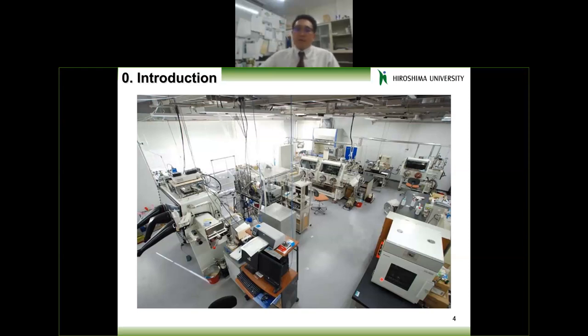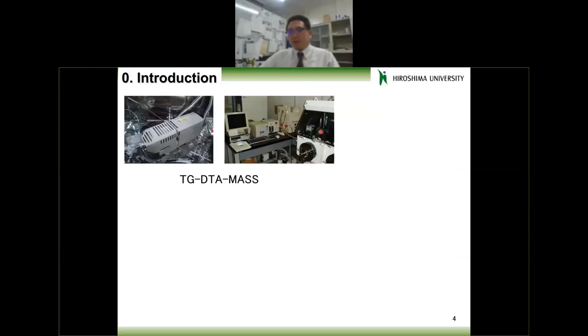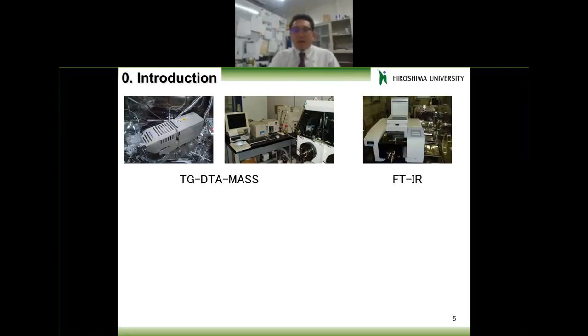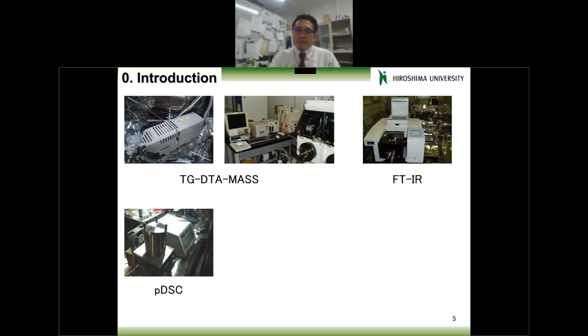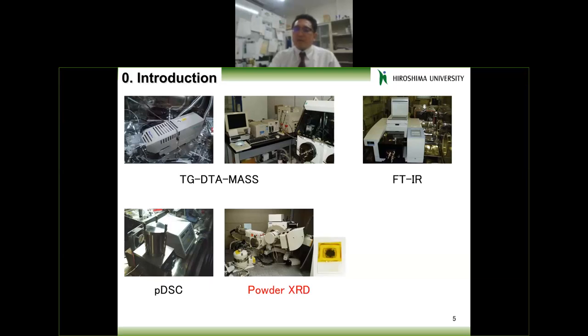This is a quite typical TG thermogravimetry and DTA mass spectroscopy, but those apparatuses are also located inside the glove box. That is quite a typical situation in our group. This is also FTIR and pressure DSC, and the pressure DSC is also set up inside a glove box. And X-ray diffraction: we measure totally without exposure to air by using polyimide film. That is a totally non-oxidized and non-water-adsorbed state, so we can characterize in quite some detail.